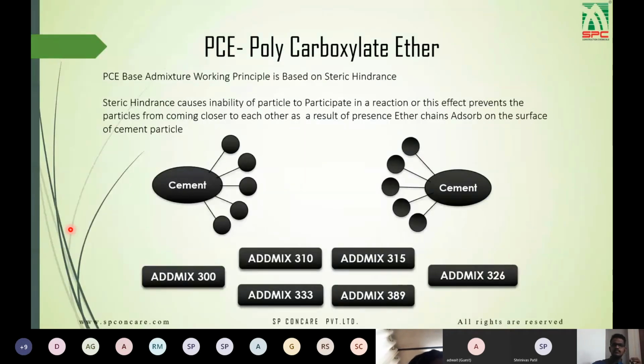The next is polycarboxylate ether. The PCE, polycarboxylate ether, works on the principle of steric hindrance. So what is steric hindrance? We can say the steric hindrance causes the inability of the particle to participate in a reaction, or this effect prevents the particles from coming closer to each other as a result of the presence of ether chains adsorbed on the surface of cement particles. Now when we add PCE base or polycarboxylate ether base admixture into the concrete, it deposits the ether chains on the surface of the cement particles.